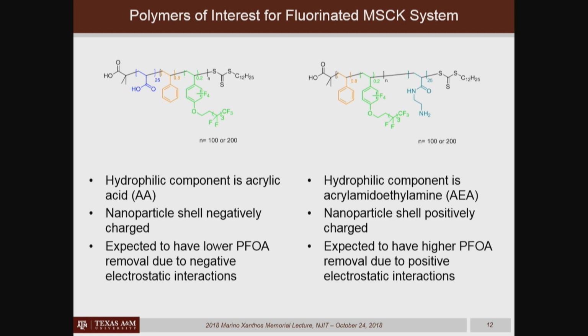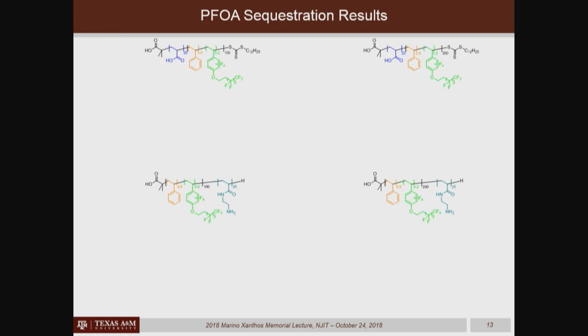So she made a series of these polymers having various relative lengths of the hydrophobic block segment relative to the hydrophilic in each case, where she had, say, a relative value of 100 repeat units to 25, or doubling that to 200 in each of these cases. And then she assembled each of these into nanoparticles together with the iron oxide nanoparticles, cross-linked the shells, and then evaluated their ability to capture perfluorooctanoic acid from an aqueous D2O solution where she could use fluorine-19 NMR spectroscopy for quantification.